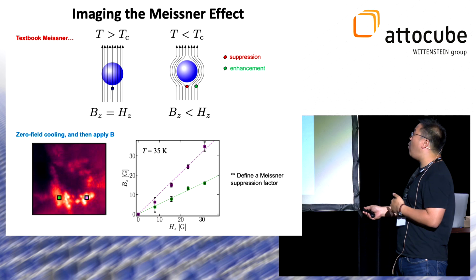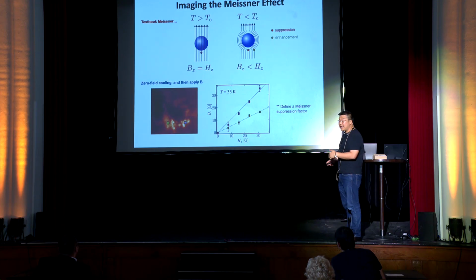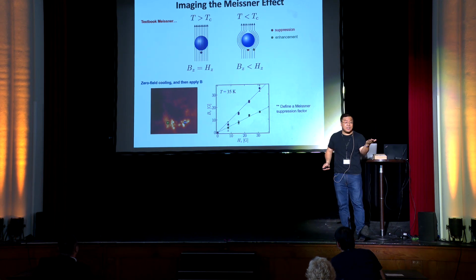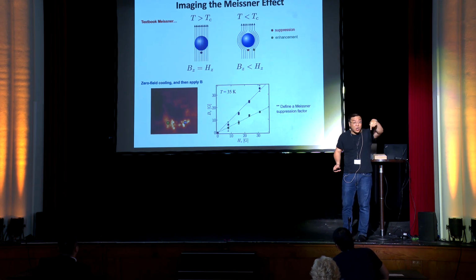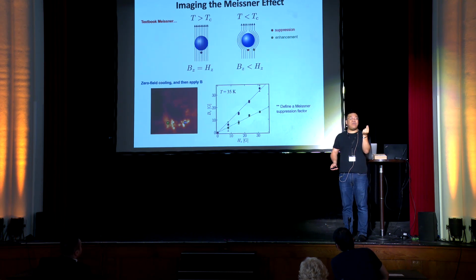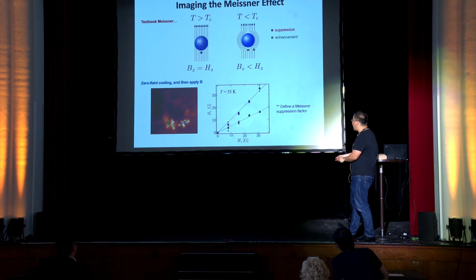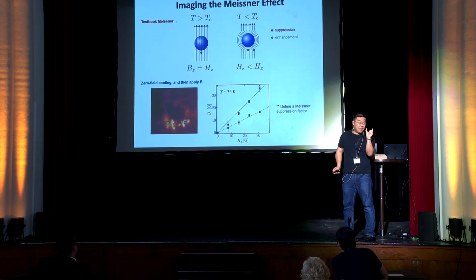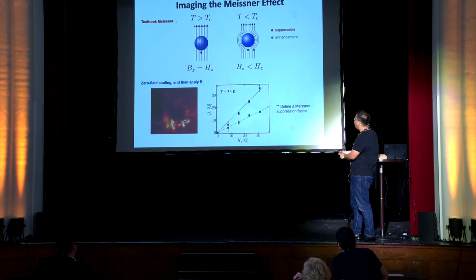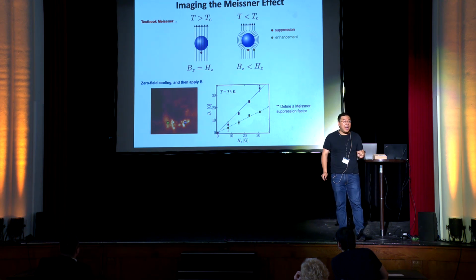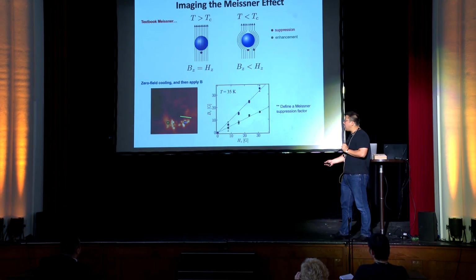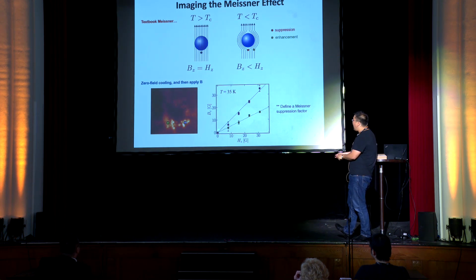So the typical thing that one does is if one is far away from the sample, one can certainly calibrate the strength of the external field that one applies. And if one's far away from the sample and one looks at a single confocal spot, you can measure what is the magnetic field measured by the NV centers relative to the magnetic field applied by the solenoid. So the applied magnetic field, Hz, is always H on the x-axis, and the magnetic field measured by the NV via Zeeman splitting is Bz. And if you're far away from the sample, you actually get essentially a line that's literally y equals x. So it tells you that the magnetic field that the NV center measures is exactly the same as the magnetic field that you're applying. But actually, at different points, and we'll be able to say why this is in a second, at different points you can actually see that the magnetic field measured by the NV center is smaller than the external magnetic field.